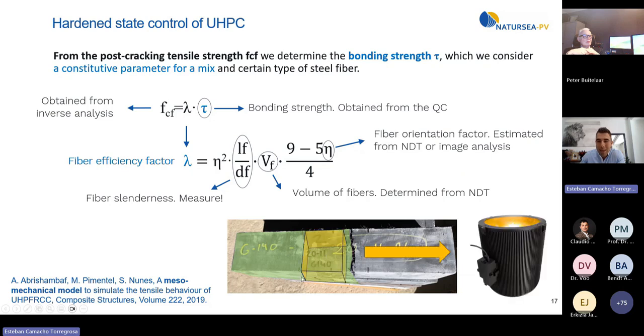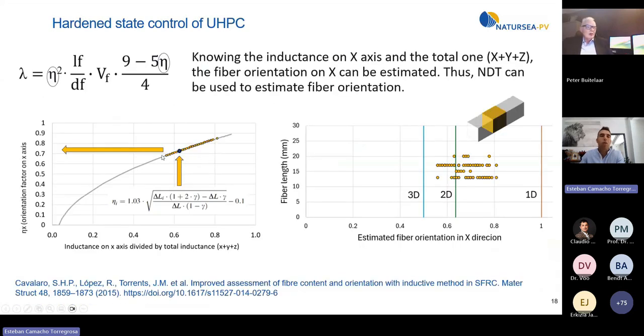How? We extract a cube of 100, 100, 100, and we introduce it in the device to determine the volume of fibers and also the fiber orientation, because the fiber orientation matters in the direction of the stresses. We can determine this fiber orientation because we know that there is a clear correlation between the inductances in each of the three axes and the fiber orientation on each of these axes. So we can estimate, based on the result, the average fiber orientation in each of these axes. What I am explaining is the left figure. We know this X value.